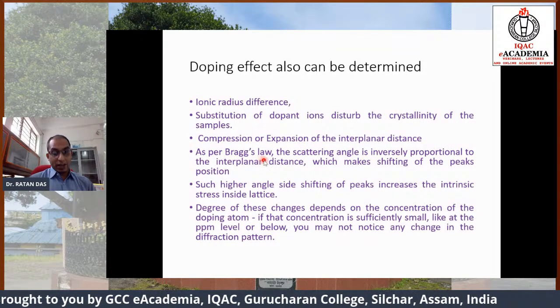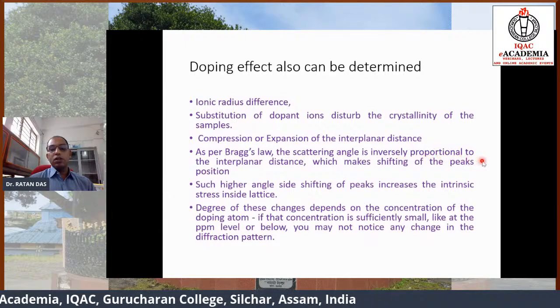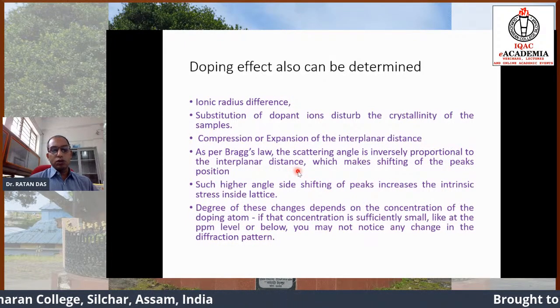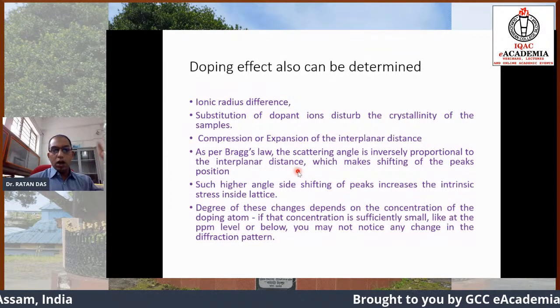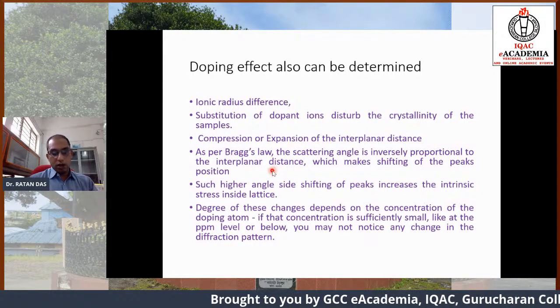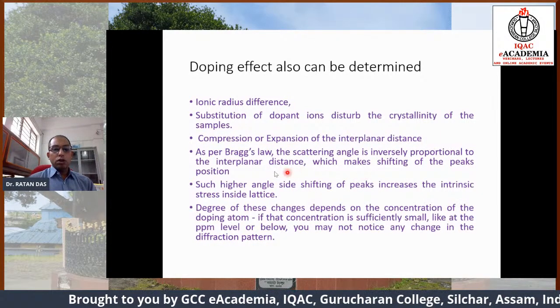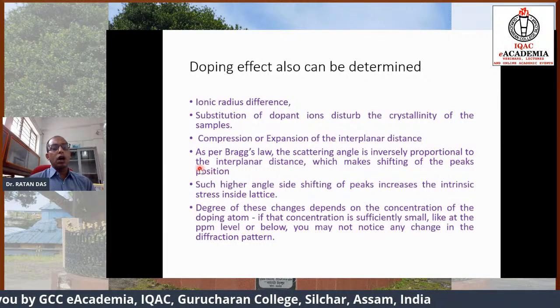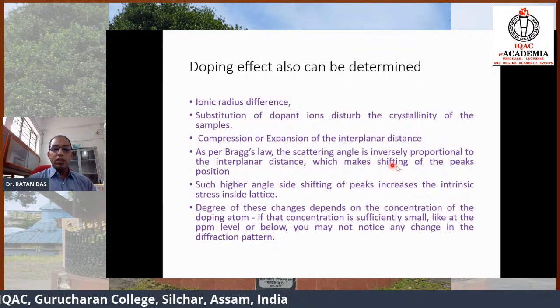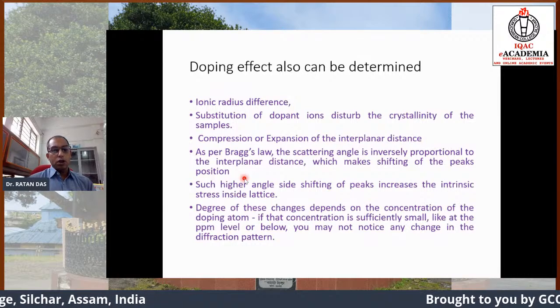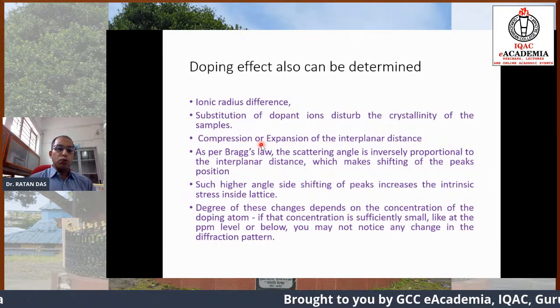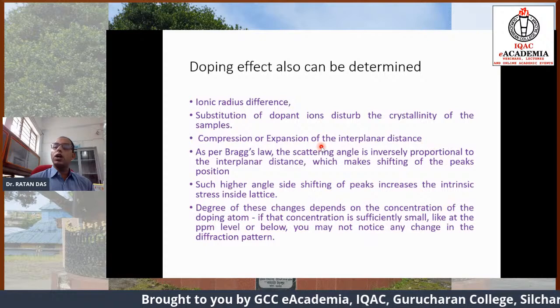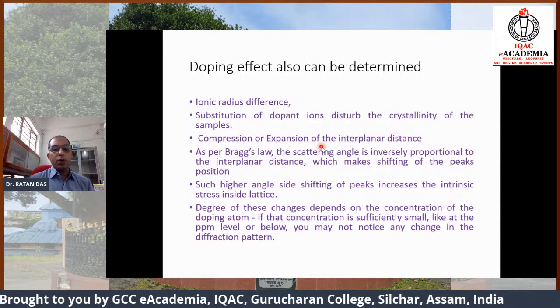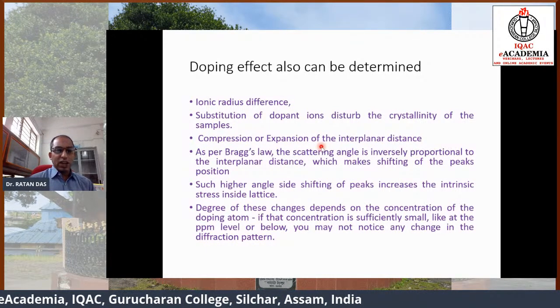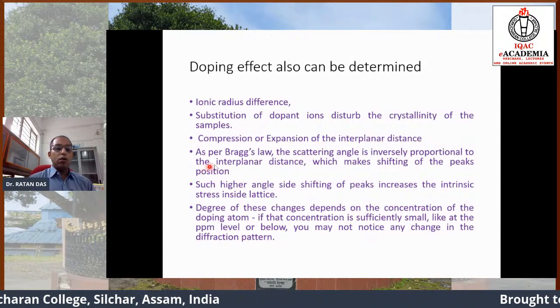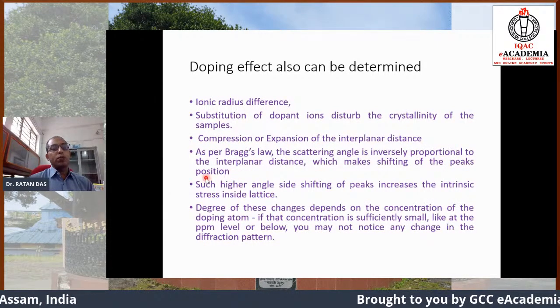Now, as per Bragg's law, 2d sin theta, the scattering angle is inversely proportional to the interplanar distance, because that d is coming into the picture. So the scattering is inversely proportional to the interplanar distance, which makes the shifting of the peak position. So if we dope the sample, there may be compression or expansion of the interplanar distance, and because of this expansion or compression, the shifting of the peak position takes place.